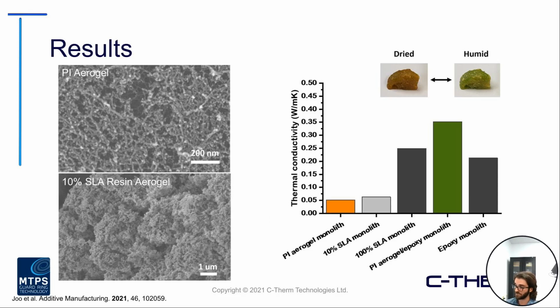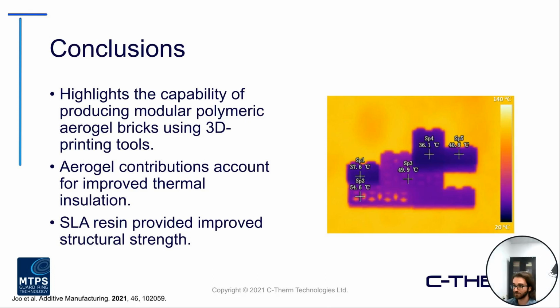Of course, the PI aerogel monolith had the lowest effective conductivity. As you increase the polymer component with respect to the aerogel amount, those properties do change, and we see a net increase. But across the board, fairly low conductivities were observed. In conclusion, they were able to really highlight the capability of producing these modular polymeric aerogel bricks with this 3D printing technology. So lots of interesting work is coming out with 3D print AM processes. The aerogel contributions really accounted for the improved insulative performance, whereas, not noted here explicitly, the SLA resin really provided structural strength that benefited the mechanical side of things.